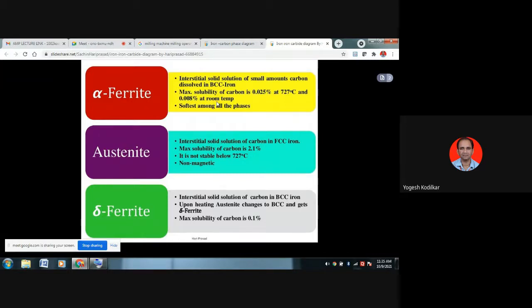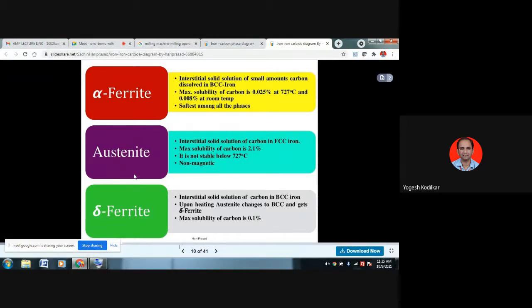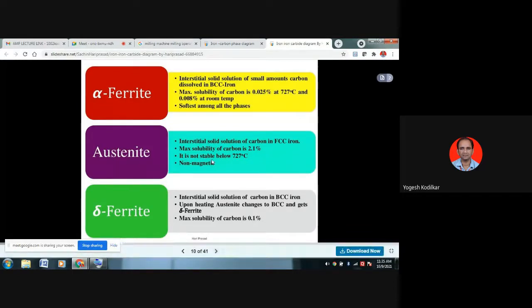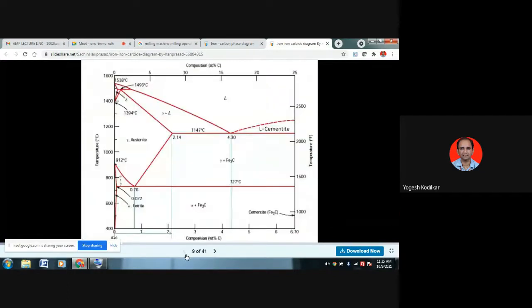Then the next phase: that alpha ferrite phase is converted to the gamma austenite phase. So gamma is again an interstitial solid solution of carbon in FCC iron. Here in alpha ferrite it was BCC iron, now in austenite it becomes FCC iron. And the maximum solubility of carbon is 2.1%. It is not stable below 727 degrees Celsius. So up to that it is stable.